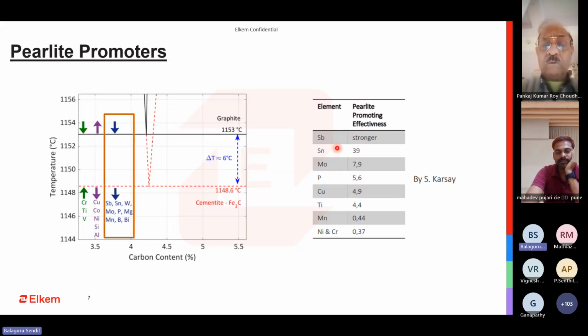So the reason here is that even this can be 0.0005. The potency of this particular element in promoting pearlite is extremely high. So this is what I would like to show here. When you have this one, the window also kind of enlarges. It pushes down the transition temperatures further down. So that is why it enables you to promote pearlite.